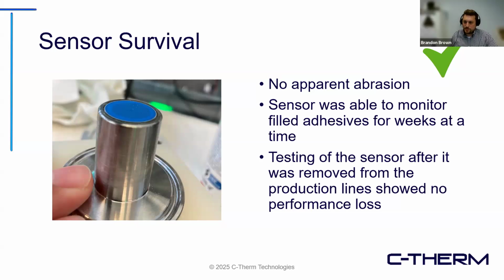After we'd gathered all the data and everything was completed, the sensor was removed and inspected, and we haven't seen any abrasion from any of our testing over the years. One of the theories we had was that the material was moving slowly enough past our sensor that any of the abrasive materials actually rolled over the surface instead of ablating or abrading it. But the end of it is that we didn't see any sensor abrasion, and Till's got some microscopic pictures in his section later on. Actually, it's back to Till.